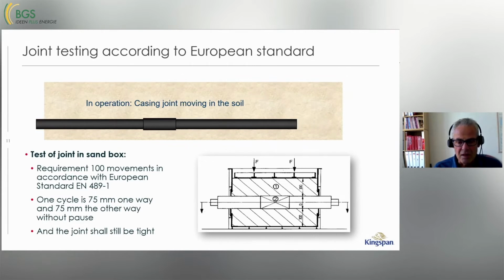After that test, it will be tested if the joint is still tight. And to be able to prove that we are conform to the requirement in the standard, the joint shall still be tight. And it is. So it is a very tough test, but with the cross-link joints, there's no issue in complying with the requirement in this test.